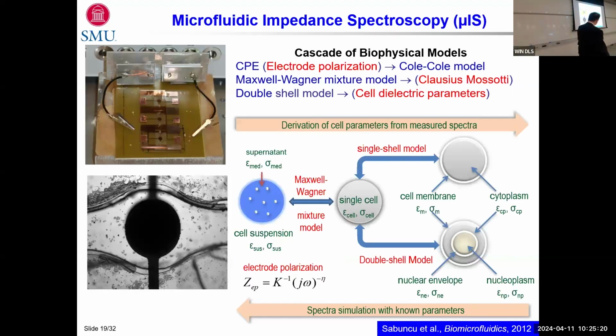So, about 2012 era, we built this simple device, which is a microchannel, and we have 2 electrodes on top and bottom, and we fill this with a fluid with cell suspension. And the key is, of course, you need to create an electric circuit model of this kind of system. And when you do that, you have first the electrode polarization effects, which especially become very dominant with small electrode size and high conductivities. And that's handled by a constant phase element model. And I'm going to talk about that very briefly later on.